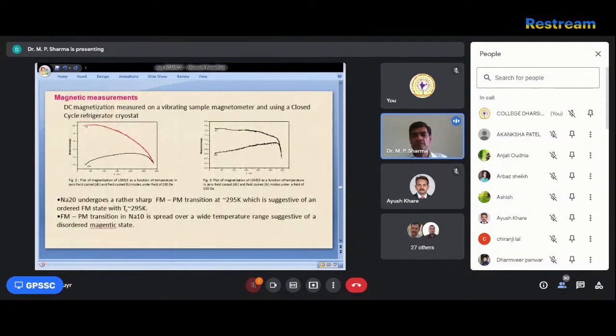So this is the magnetization we have taken for both of the samples, 0.1 and 0.2. 0.1 doping, and another is 0.2 doping. This shows ZFC and FC. ZFC means zero field cool, and the other is FC, field cool. It means first we apply zero field and cool down the sample up to 0 Kelvin, or there is a facility to cool down to 10 Kelvin. So we insert the sample in the cryostat, apply exactly zero field, and cool down the samples, and then apply the field and take the measurement in the warming cycle.